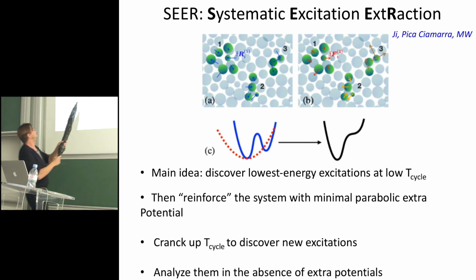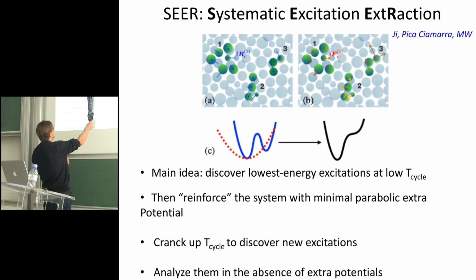Okay, so here's the idea. You take your system, you equilibrate it, you quench it, and then you excite it, and you find the first excitation. Let's say the lowest one was this. In a nutshell, what we do is that once we find it, we're going to heal this, to strengthen the system here, I will tell you how, so that nothing can happen there anymore. And then you continue cranking up the temperature, and so you will discover another one. And then again, you heal the system here, you strengthen it, and there is no problem there, and then you increase the temperature and you detect more and more of those excitations.